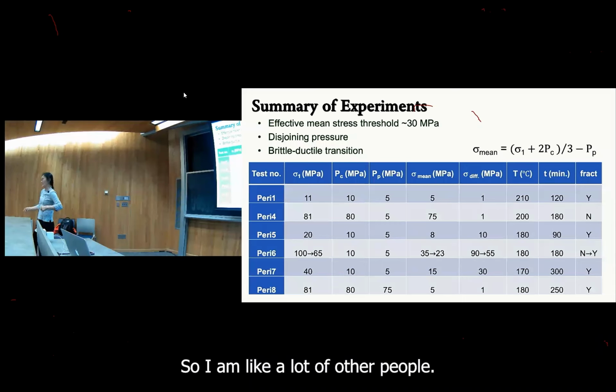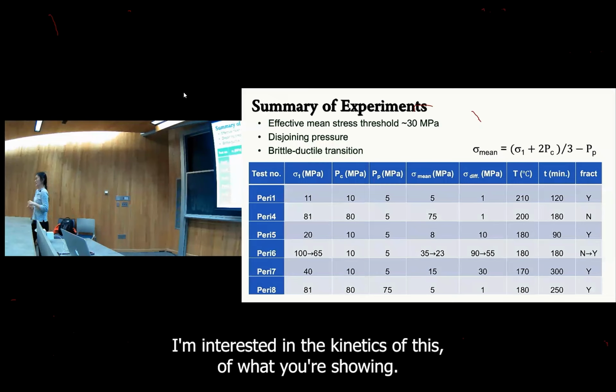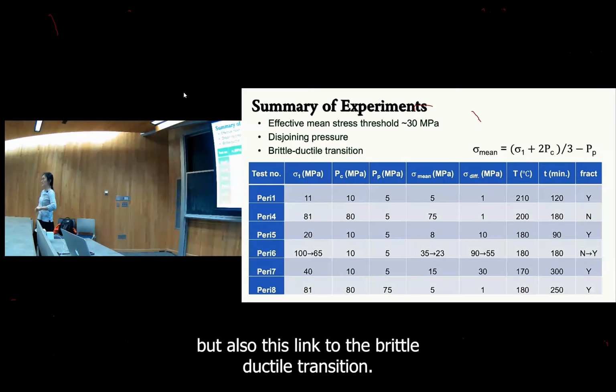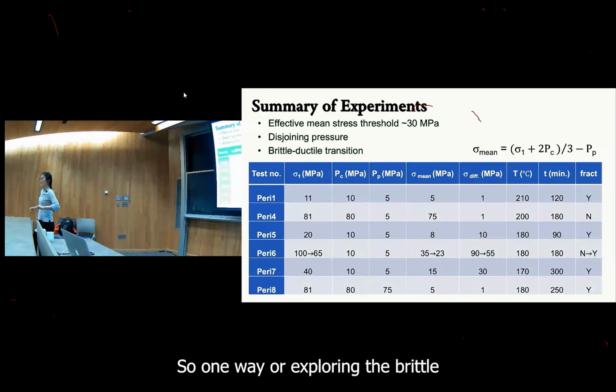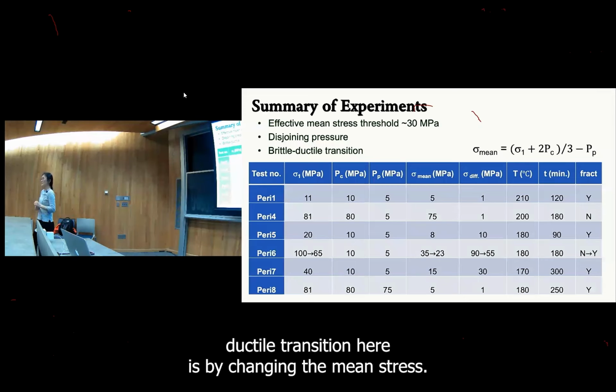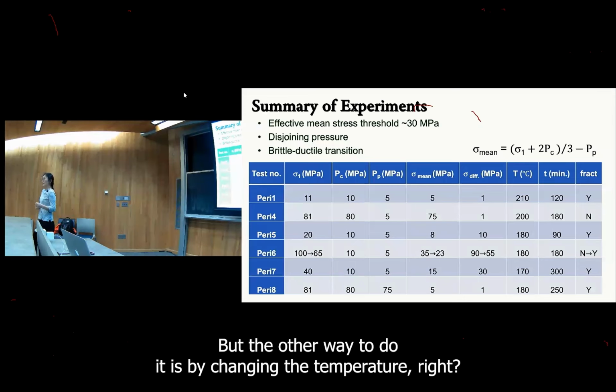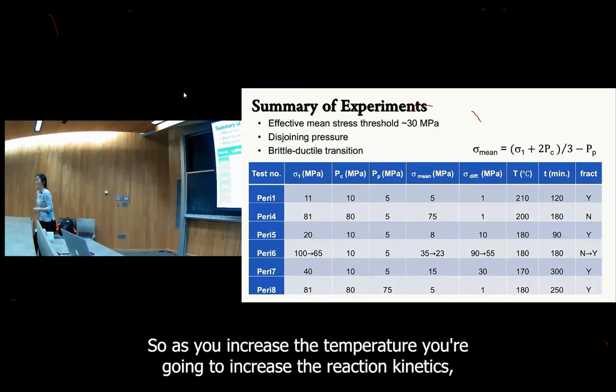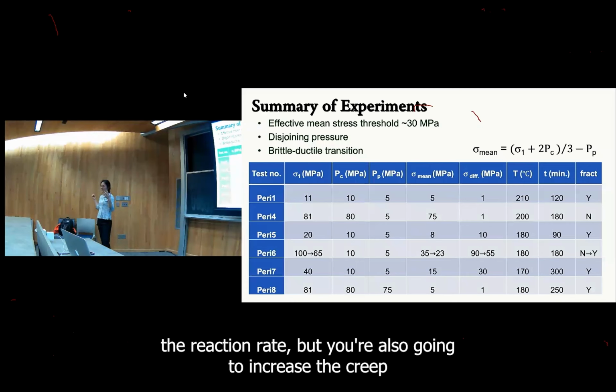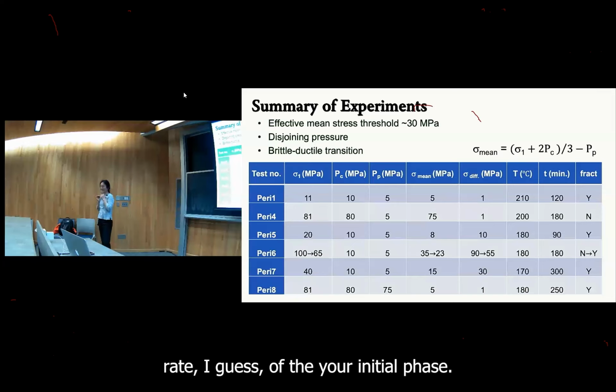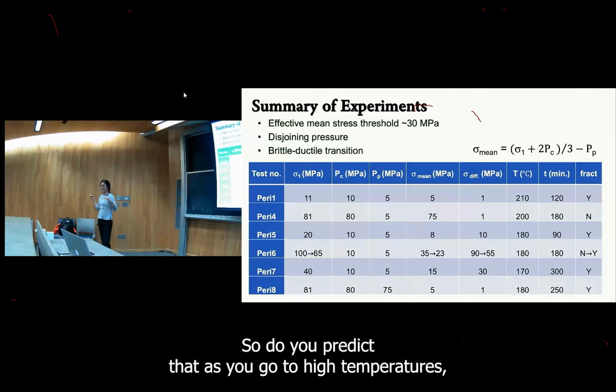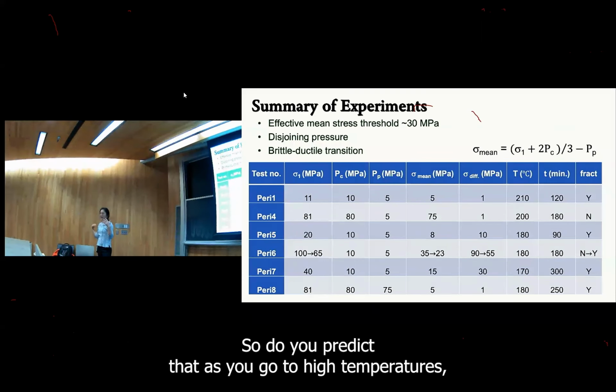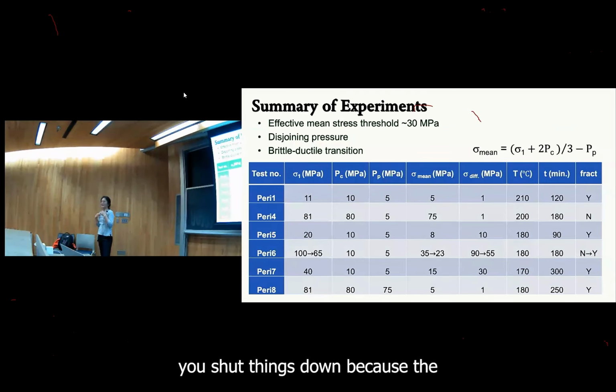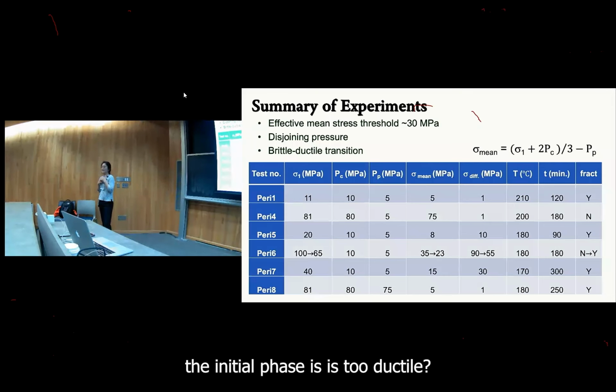I'm, like a lot of other people, interested in the kinetics of what you're showing, but also this link to the brittle-ductile transition. One way you're exploring the brittle-ductile transition here is by changing the mean stress. But the other way to do it is by changing the temperature, right? As you increase the temperature, you're going to increase the reaction kinetics, the reaction rate. But you're also going to increase the creep rate, I guess, of your initial phase. So do you predict that as you go to high temperatures, you shut things down because the initial phase is too ductile?